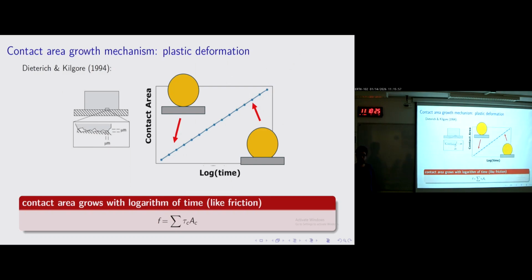Why is that? Well, people typically think of that in terms of contact area growth. The idea is that, remember these small asperity contacts, because they're quite small and we have quite a bit of load on the block, they can deform plastically. What do I mean? They squish and change shape, and by changing shape, the contact area actually increases. If we idealize one contact as a sphere on a rigid flat, then at the beginning of a hold the contact area is pretty small, but over time the sphere is going to squish, the contact area is going to increase, and that means contact area grows. So when contact area grows, friction grows as well, and that's why we see this frictional behavior.